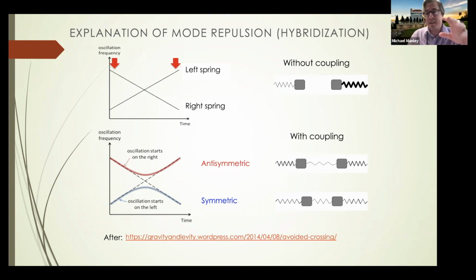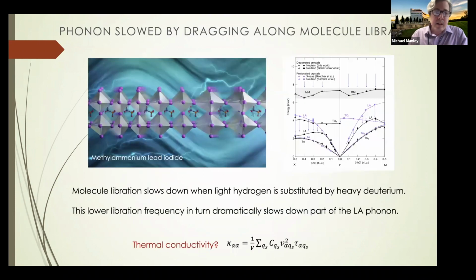It's kind of a general concept, but it applies all over the place in spectroscopy. If you don't understand that in detail, the main picture to think about is that you have this vibration that is propagating, say, in this image here, and it's a compressional wave. So it's squeezing, expanding, squeezing, expanding. And as that happens, if the molecular mode, this libration, has a frequency that gets close to it, then it's going to start to drag it along. And that lower mode is going to basically be dragging this thing along, and it's going to slow down the phonon. And so that's basically what's happening.